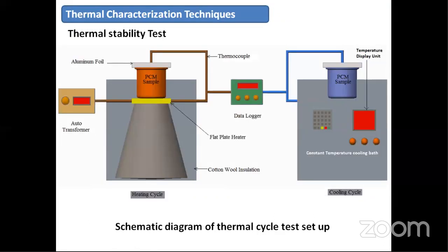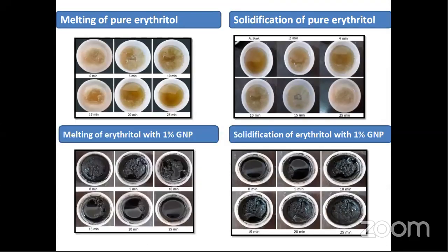Then thermal characterization techniques, so thermal stability test or thermal cycling test. The thermal cycle test is used to know the long-term stability of the storage material. The thermal cycling system was designed to operate between 30 degrees Celsius and 140 degrees Celsius. Totally 1000 cycles were taken. Each cycle contained one melting and one freezing process. These are the physical states of the PCM and the NDPCM samples during the melting and solidification process, shown in the figure.